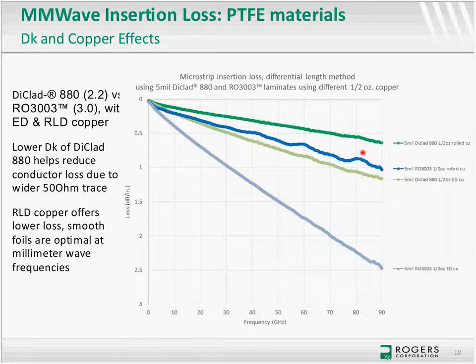For the loss materials, you'll see here the impact of rolled copper versus electrodeposited copper. You can see the difference that happens with this material. This is very thin dielectrics, 5 mils, versus the RO3003, which is a PTFE ceramic product from Rogers. You can see the impact of rolled copper versus the ED copper difference. So you can see definitely that when using rolled copper with these various materials at higher frequencies, there's a significant benefit to that. So that is important for the higher frequency bands.